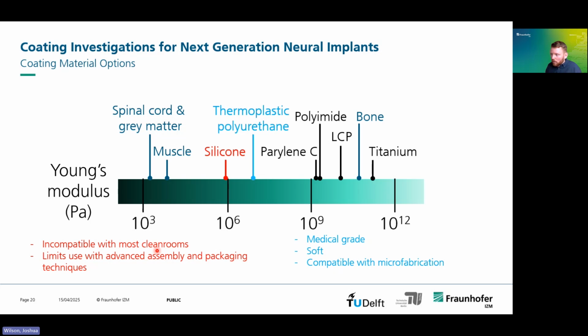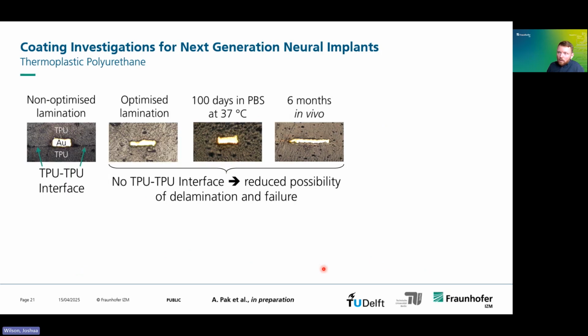And a good alternative option, we feel, is thermoplastic polyurethane. This is also medical grade, very commonly used. It's very soft as well, not quite as soft as silicone, but very soft. And it's compatible with microfabrication, which is very important. Now, if we take a look at this polyurethane, if we start to build a device, then we will have a TPU, a thermoplastic polyurethane substrate, and we will do some lithography processing with some gold metallization, and then we laminate a second layer of TPU on top.